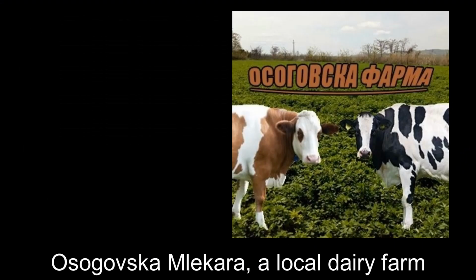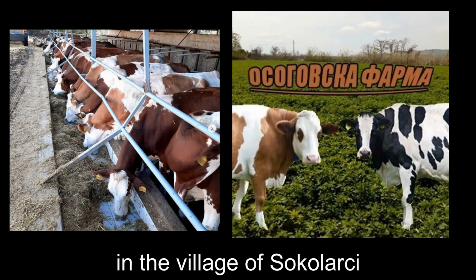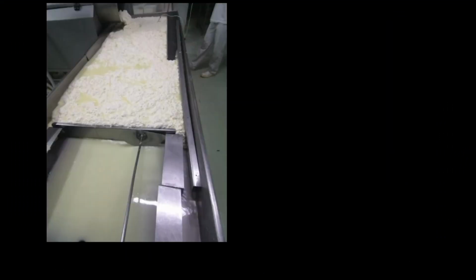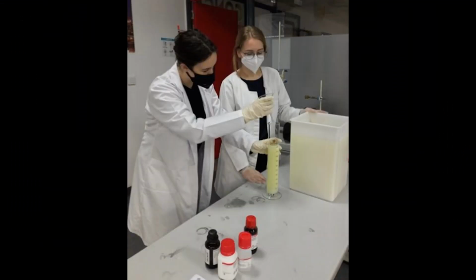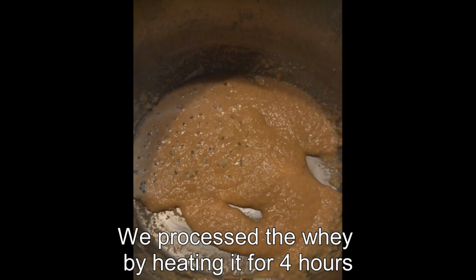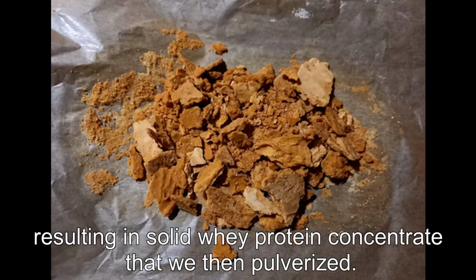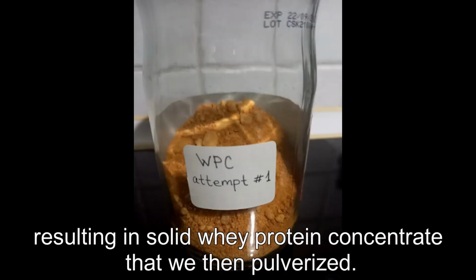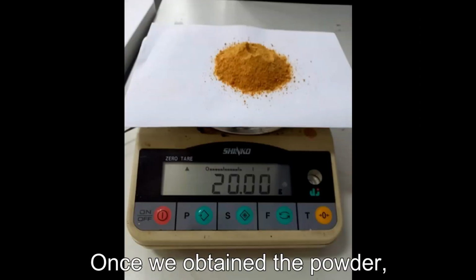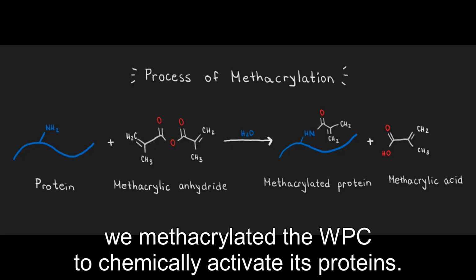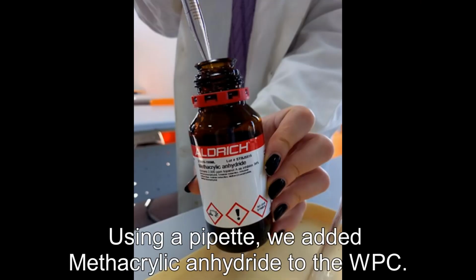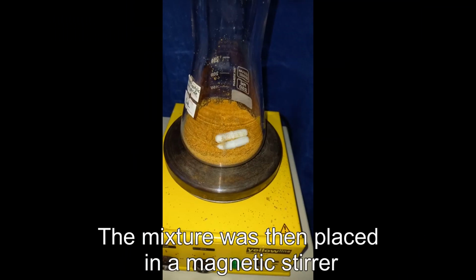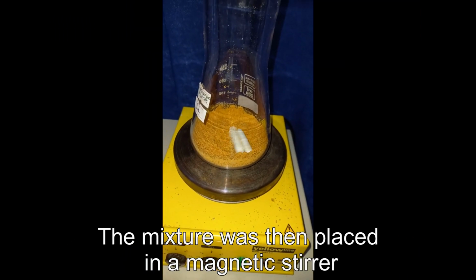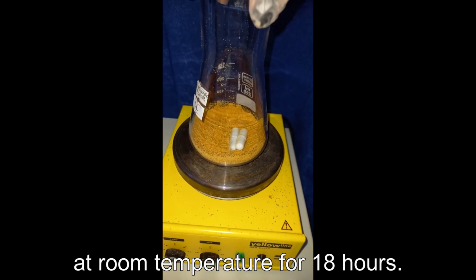Osogovska Mlekara, a local dairy farm in the village of Sokolarci, not far from our hometown Skopje, was happy to give away their excess whey to us. We processed the whey by heating it for 4 hours, resulting in solid whey protein concentrate that we then pulverized. Once we obtained the powder, we methacrylated the whey protein concentrate to chemically activate its proteins. Using a pipette, we added methacrylic anhydride to the whey protein concentrate. The mixture was then placed in a magnetic stirrer at room temperature for 18 hours.